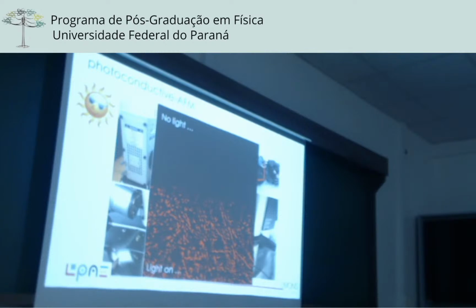So now let's move to the photoconducting AFM. With the sun, as I mentioned before, this is the way the light is coming to the device, and we use this P3HT:PCBM sample. At the beginning, no light for the picture, and then we switch the light on, and this is what we got. No light, no current; light, we have the fibrils and the PCBM. And there is no voltage applied to the system. There is no DC polarization, which means that the current that you see there is really a photocurrent generated by a photovoltaic